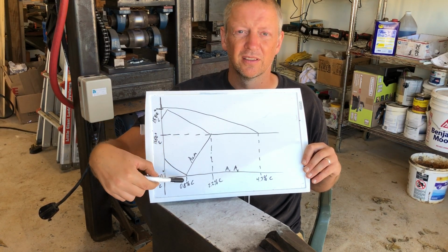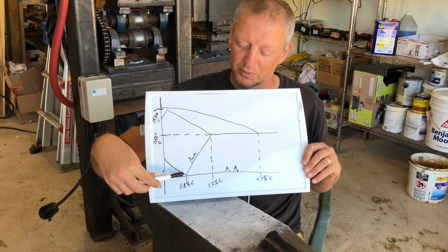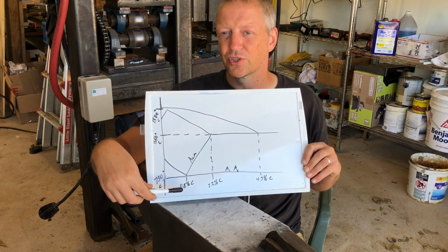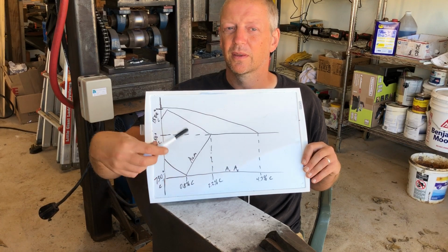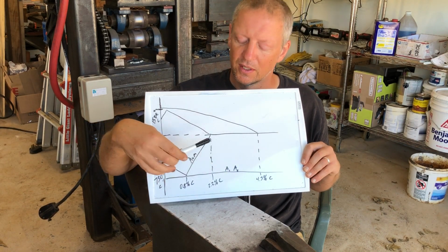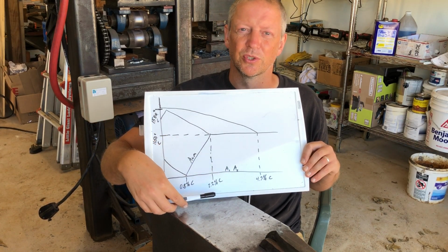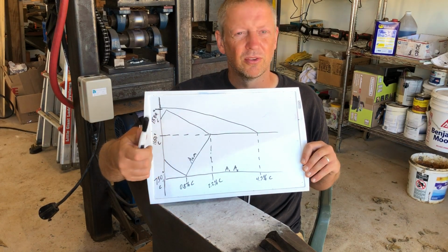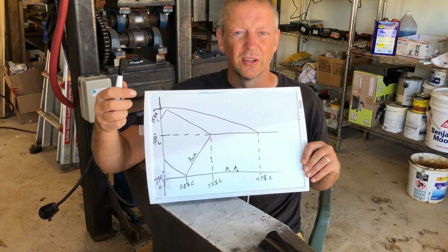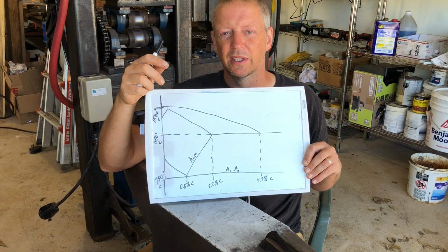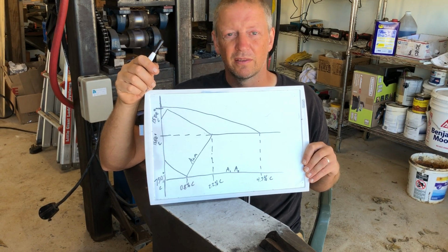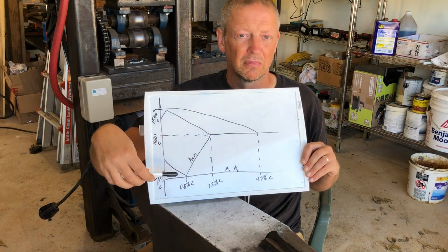However, when cooling, you will probably find that you could forge to a cooler temperature without having awful things happen because that transformation temperature is depressed. So that's a way in which you can actually witness this line in your forging.